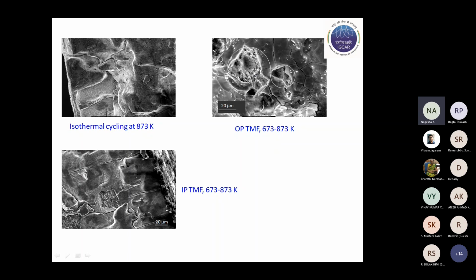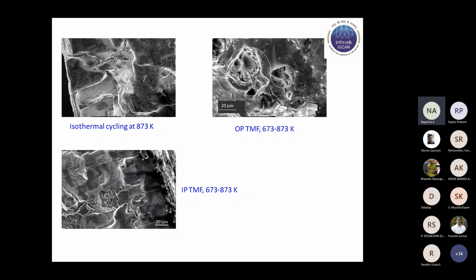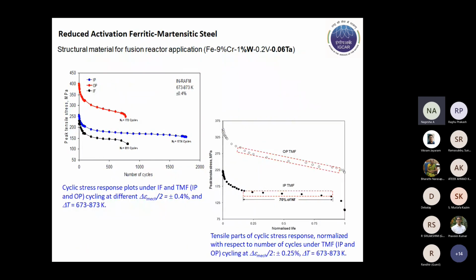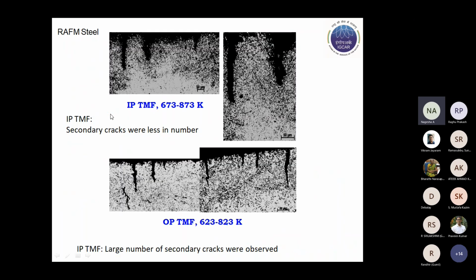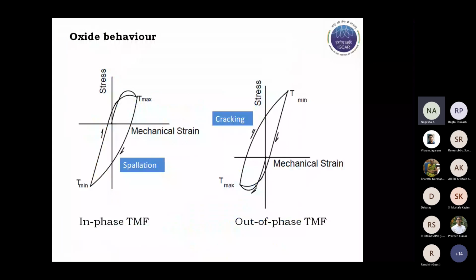Substantial cracking of this oxide layer, coupled with significant internal oxidation, is seen in the case of OP TMF. This is coupled with the mean tensile stress, because the tensile stress is much higher in OP compared to IP. You can see in this figure, tensile stress is much higher compared to the other two cyclic loadings. So a combination of the oxidation-induced damage and the higher tensile stress gave rise to a lower cyclic life in OP TMF in these materials. It was the case both with the 9Cr-1Mo steel as well as the reduced activation ferritic martensitic steel.